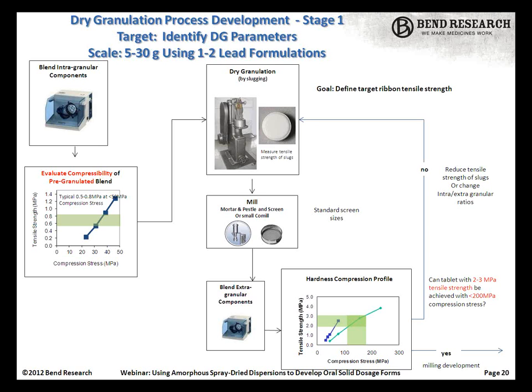So what we're assuring at this point is that we have adequate compressibility of our dry granulation, and we will target at this point to assure that our final blend has a compressibility of about 2 megapascals. So we'd like to be able to achieve up to 3 megapascals to give us some flexibility here. So that would be our target at this small scale. Maybe 1 to 3 megapascals of our final blend is what we're targeting here.